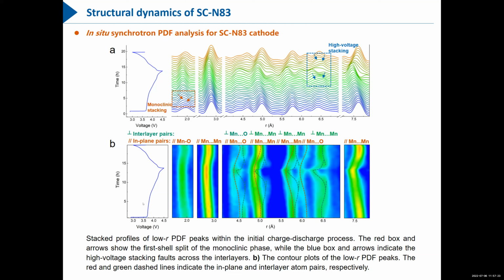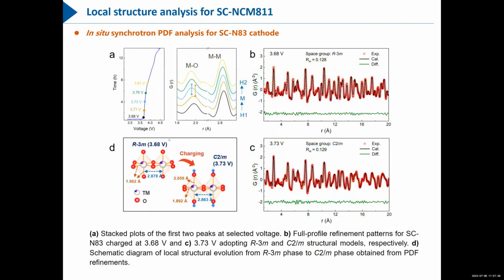This is how this kind of phase transition happens in these materials. Once again, this kind of phase transition has never been found in polycrystalline structures when I studied them; it has only been found in the single crystal structure. So we believe this kind of phase transition could be very useful for the capacity retention of these materials. Now there are only a few minutes left.